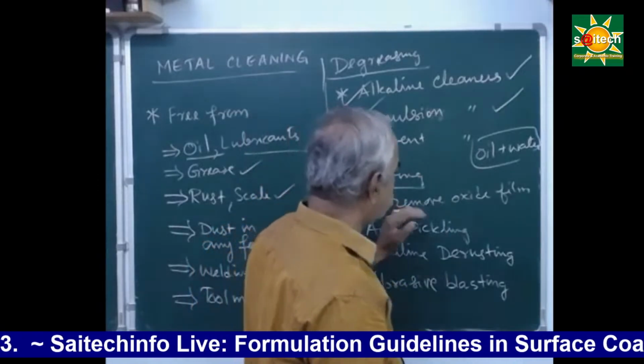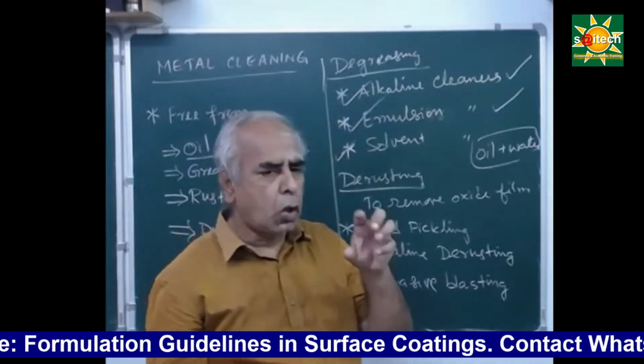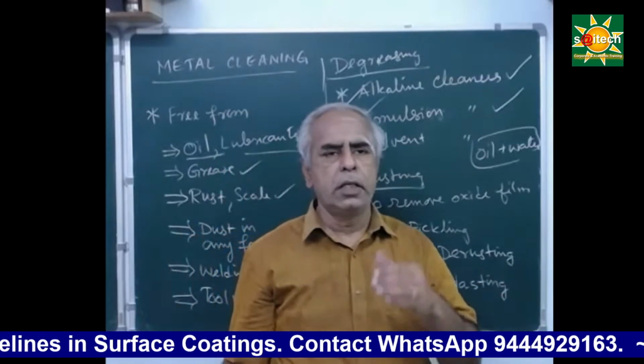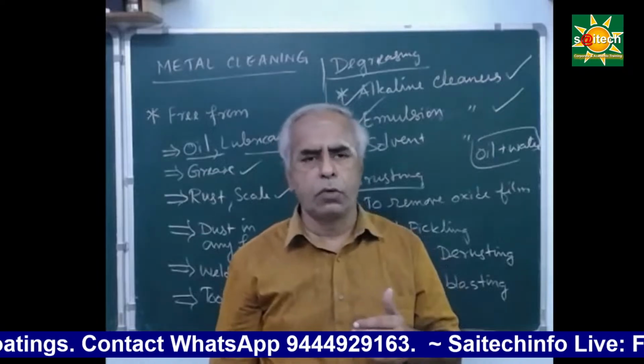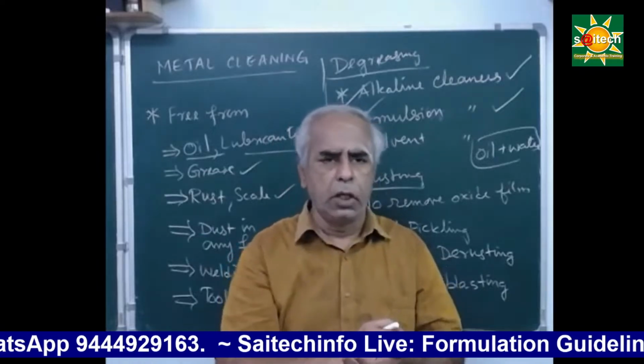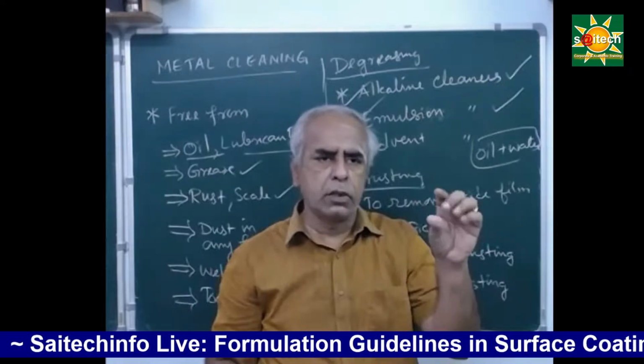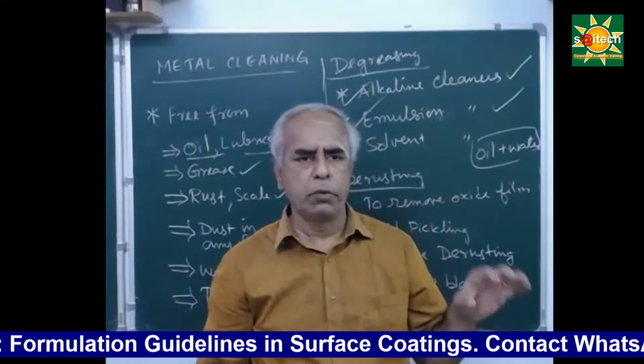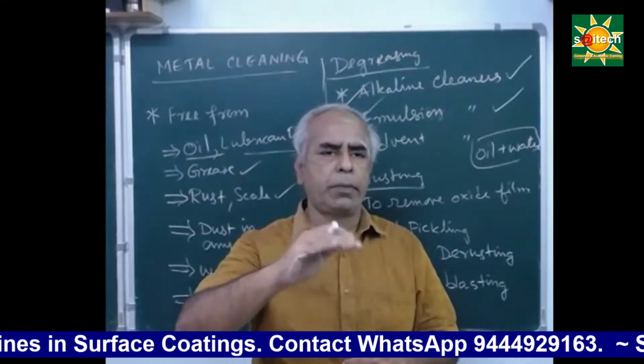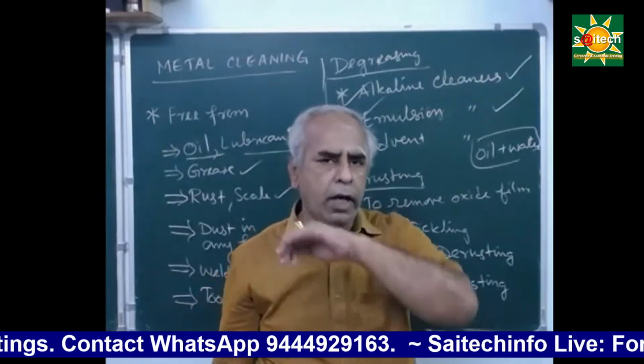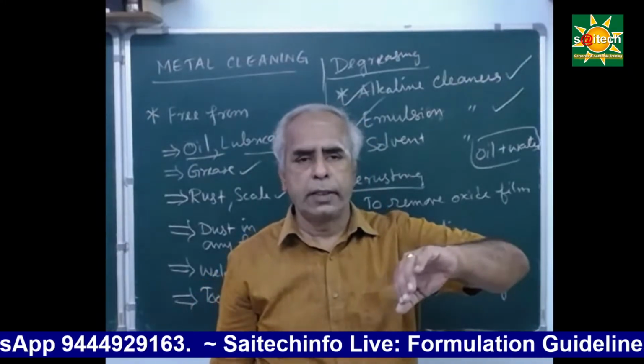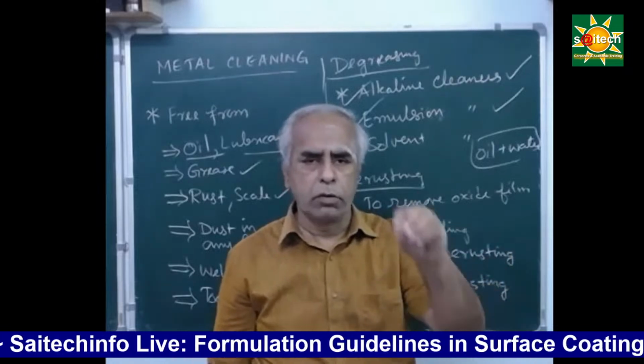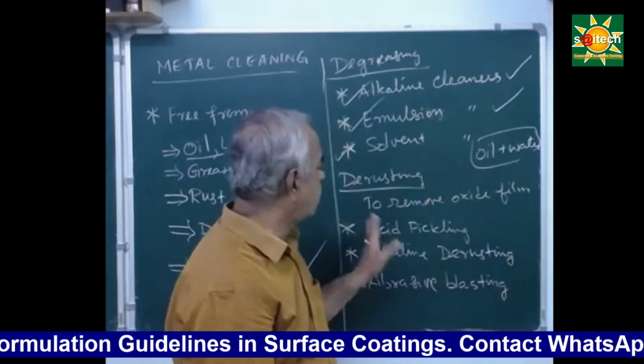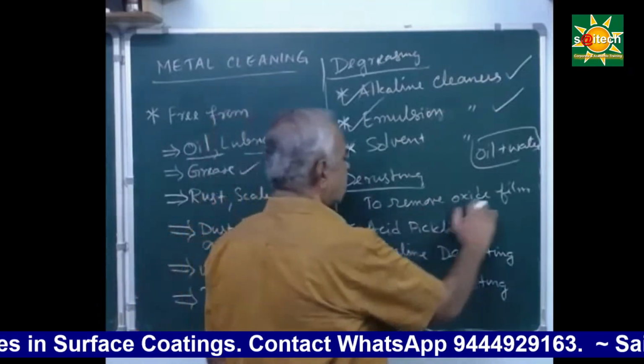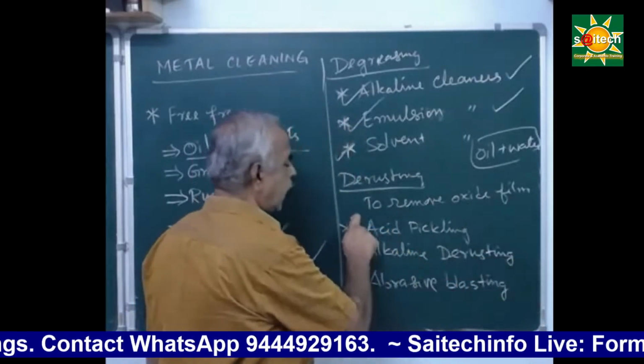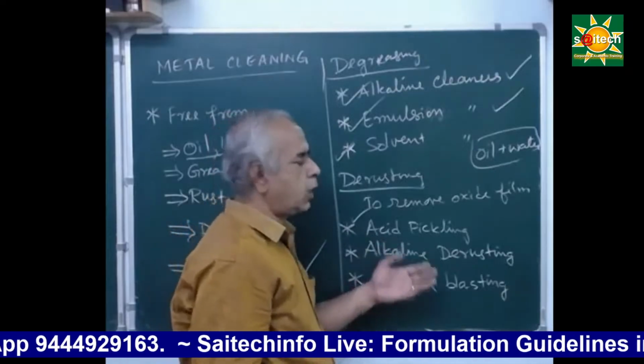Then de-rusting. De-rusting is a process where the metal oxide is removed. Rusting is the process of conversion of metal into metal oxide. That metal oxide layer is loosely held, and it should be removed, otherwise our paint will not be adherent to it. Not only that, it will be corrosive, it will cause rust, and it will result in pitted corrosion. So it has to be removed. This metal oxide film is removed by using acid, and in that case it's called acid pickling.